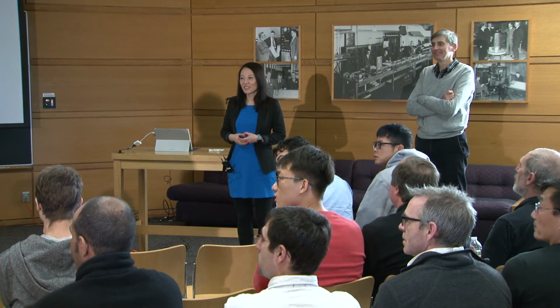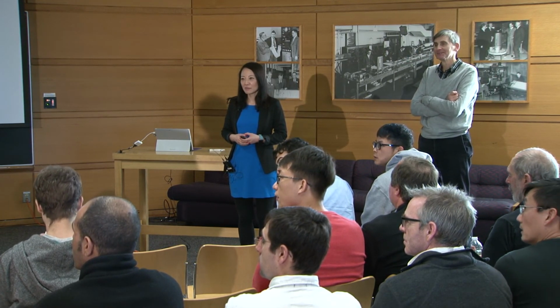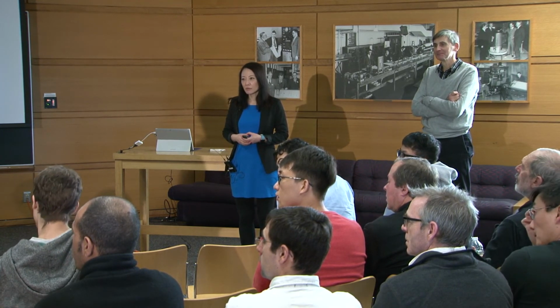Alex, that's a terrific talk. Thank you. A long time ago, I worked on the silicon dioxide interface, and we had this nitride and oxide combination that Simon Wong at Stanford developed. One of the things I think you said earlier that I was a bit confused on is that in the early parts of silicon, when it degrades, basically either a threshold shift or a subthreshold slope change, the model was that when there was a bias stress, the hydrogen could be removed and then expose the trap. And that made sense to us. What we then found was that the nitrogen that came from an ammonia piece actually removed the hydrogen, filled that trap, and kept it more stable.